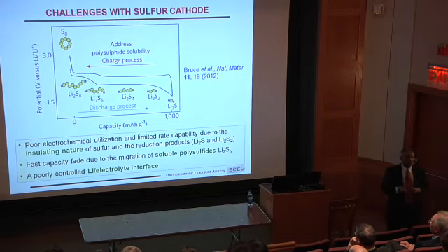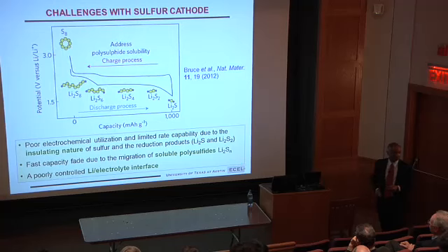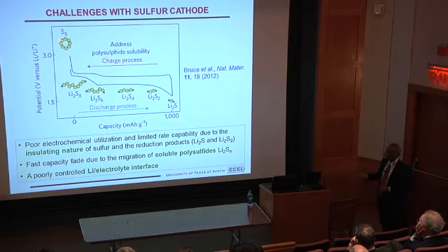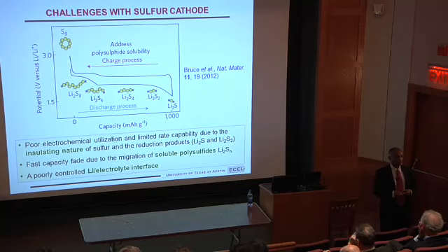So when you insert lithium, the bonds break in steps. They don't all break in one step to give Li2S from S8. It doesn't happen that way. You have Li2S8, Li2S6, Li2S4, Li2S2, Li2S. And these are called polysulfides. And they are soluble in the electrolyte. And also both sulfur and Li2S are electrical insulators, 10 to the power 15.